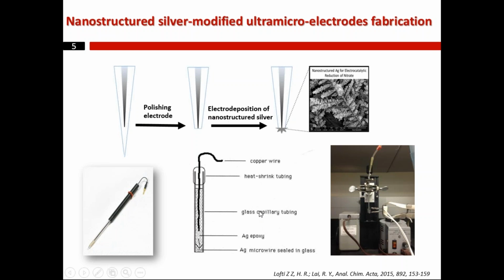Then you have to make the contact of the electrode, and you can do this by inserting a copper wire into the capillary tube, and then you have to use a type of conductive glue like silver epoxy in order to make the contact between the micro wire and the copper wire. Lastly, you have to polish the electrode until the micro wire gets out of the quartz. In this case, we made two types of ultramicroelectrodes: one time by placing a silver micro wire inside the capillary tube, and the second time by placing a carbon fiber inside the capillary tube.